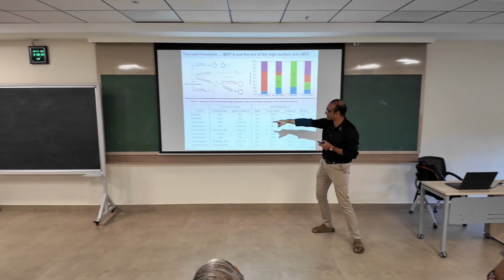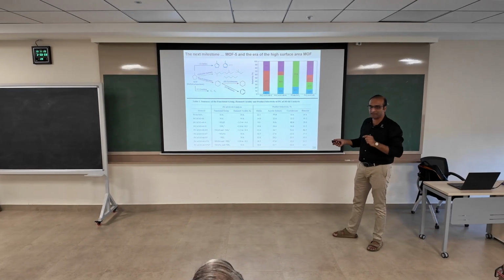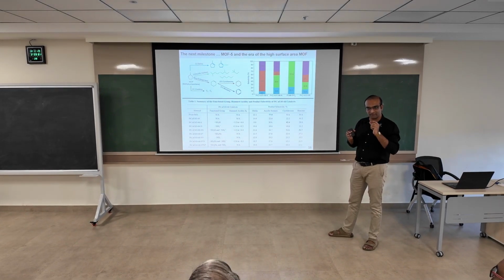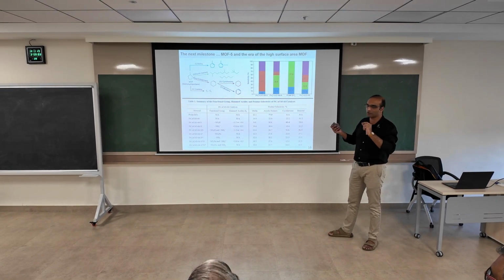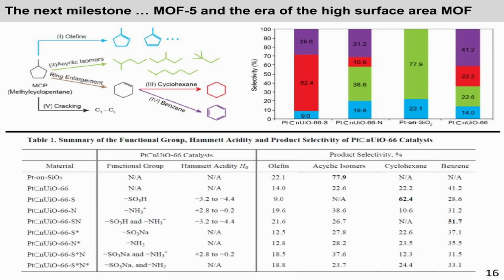So by changing this acidity and this platinum linkage, with the platinum that's inside it, it can control the way it adsorbs on the platinum, like restrict the adsorption on the platinum in certain modes. I think I'll show it better in the project I'm doing. But basically what I'm saying is, when you change the acidity of these linkages on the linker,